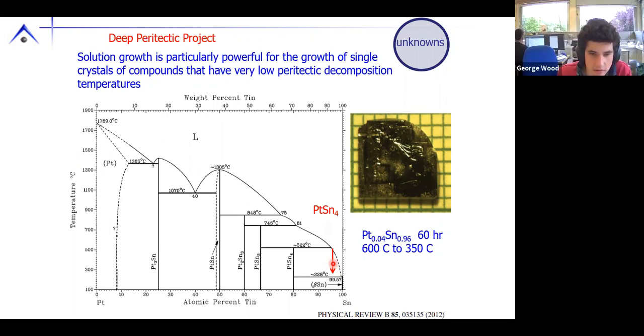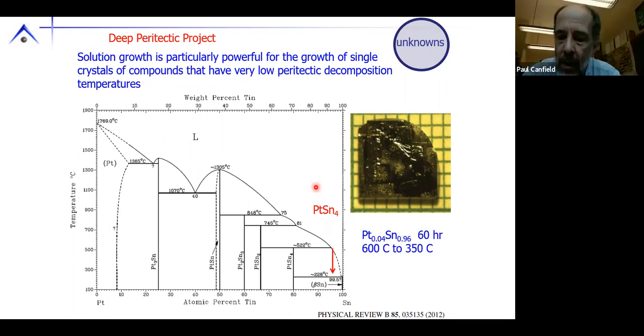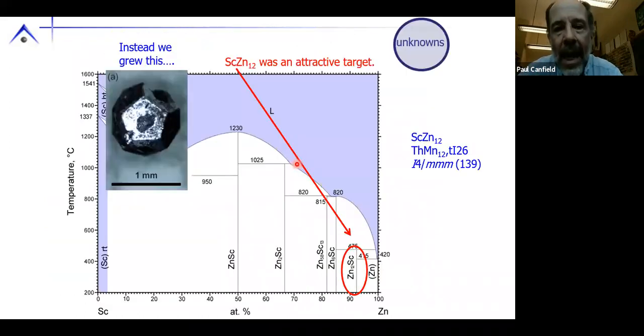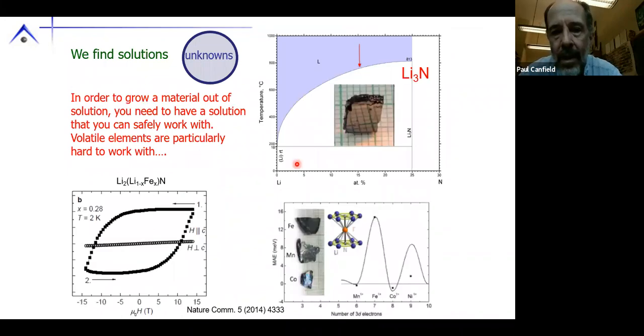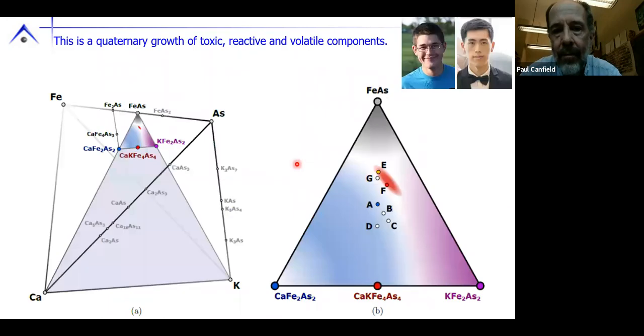So you're just accessing the correct part of that liquidus line, and then let's go back to further down where we can, like Abbott in Flatland, go to higher dimensions. Okay, so let's go to these two poor lads. Yeah, here we go. So Ty and William, you know, we're trying to grow calcium potassium iron 4 arsenic 4. In that case, you don't even have temperature shown. This is just composition inside the volume of this three-dimensional space. Now, we can reduce this to a pseudo-ternary phase diagram where we have iron, arsenic, calcium 122, potassium 122, and what we want. Okay? That the region in composition that allows us to grow this is way over here. Okay? That's way, way over.